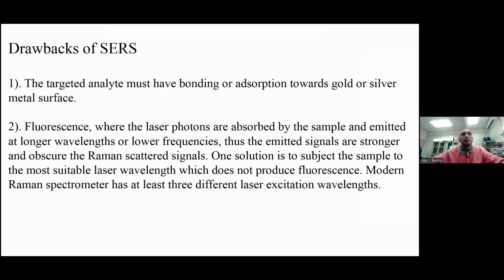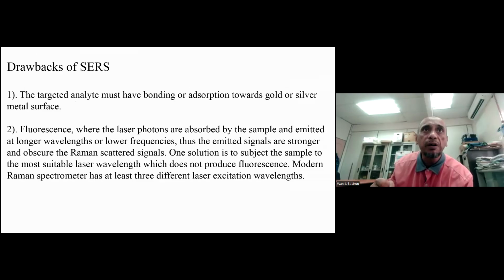Okay. So drawbacks, for example, the target analyte must have bonding with, or adsorption towards, the gold or metal surface. One main drawback is fluorescence. Fluorescence is where the laser photons are absorbed by the sample, and then signals are emitted at longer wavelength, lower frequency. Mostly it happens in organic compounds. The molecule excites and then relaxes by releasing lower frequency, so this basically obscures the Raman signal.